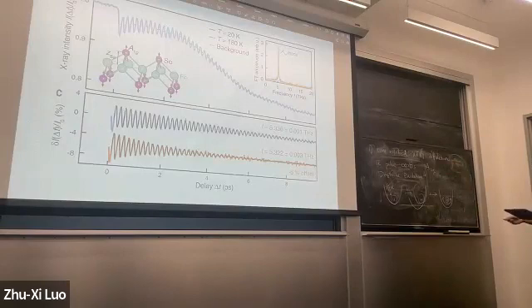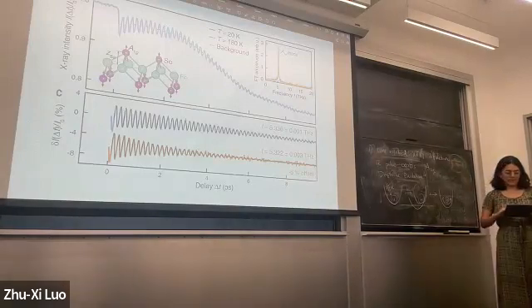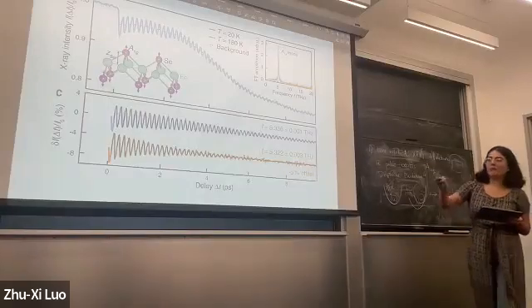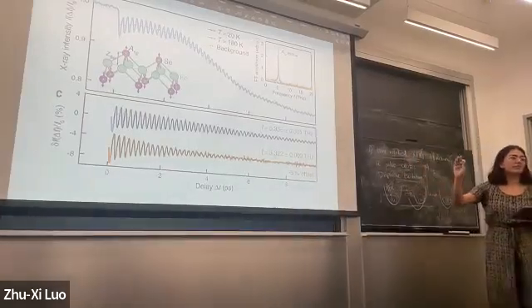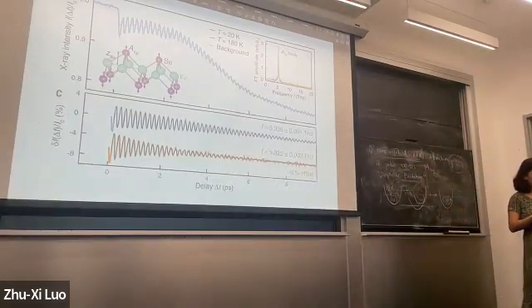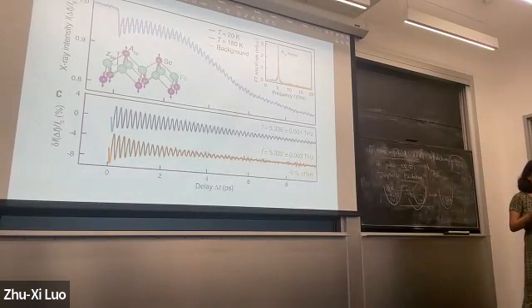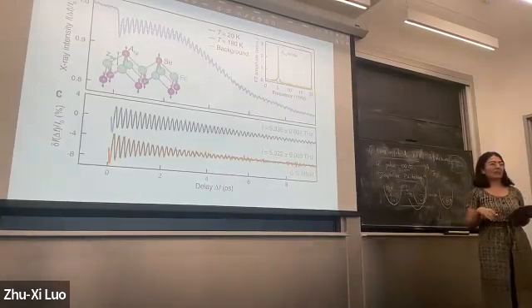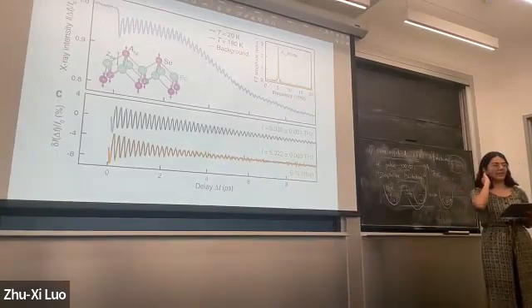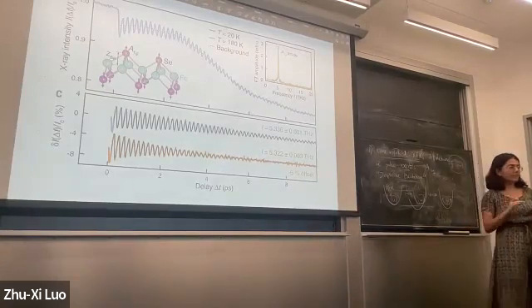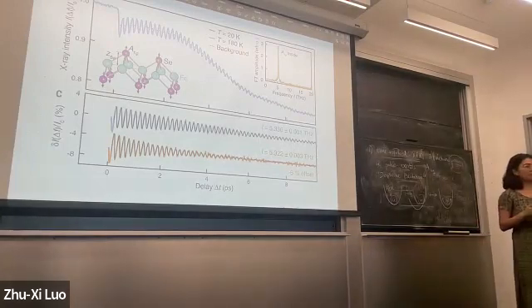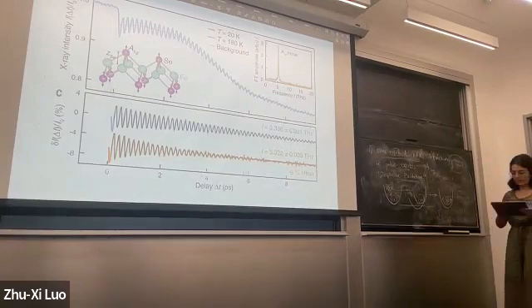Okay. And I'll note that they can extract the absolute amplitude of the displacement of the selenium atoms by doing some structure factor calculation where you assume that the selenium atom position is the only important variable, and you can back out that displacement from looking at the amplitude of your intensity oscillations.